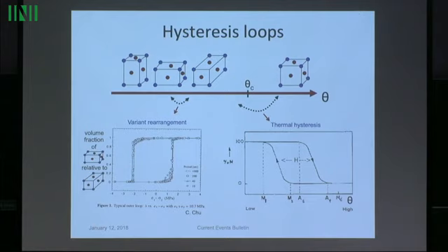That would also be true here if I transform back and forth at various periods. In fact, if I transform very fast, I would get a little bit bigger hysteresis loop. That's understood. It has to do with the fact that it takes some time to get the heat in and out of the material. But if I went, on the other hand, slower and slower, this loop would not shrink to zero as I go slower and slower around the hysteresis loop.